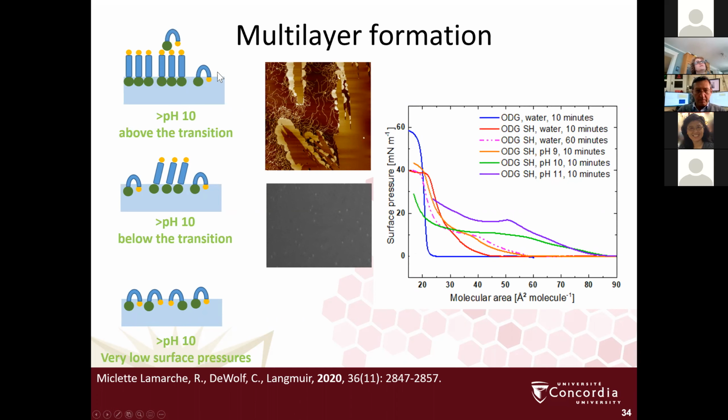The height differences imply that we still have a Bola form. And again, this very regular height difference here. This is not a random height amorphous material. We've gone across many, many different images and domains, and it's always the same height, and it corresponds to effectively the same height as you have here. So it suggests we have a Bola on top, driven by strong head group interactions.